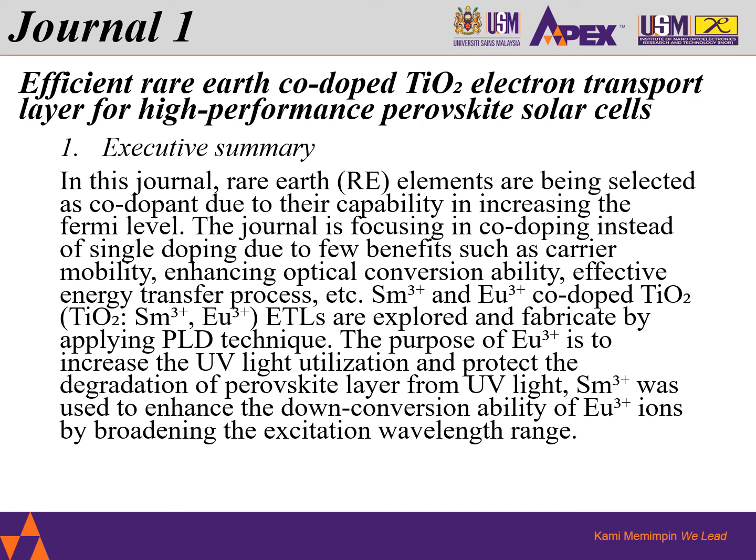This journal is focusing on co-doping instead of single doping because of a few benefits such as carrier mobility, enhancing optical conversion ability, effective energy transfer process, etc. This Sm and Eu co-doped TiO2 is fabricated by applying the PLD technique.